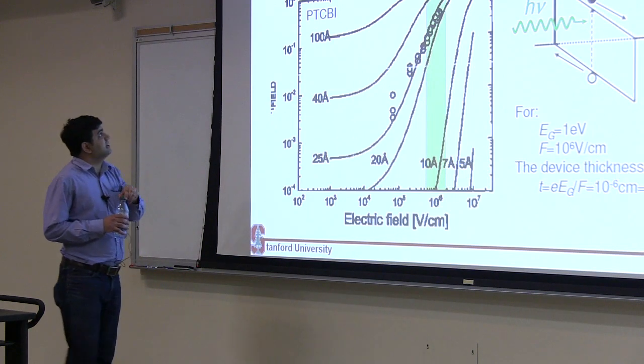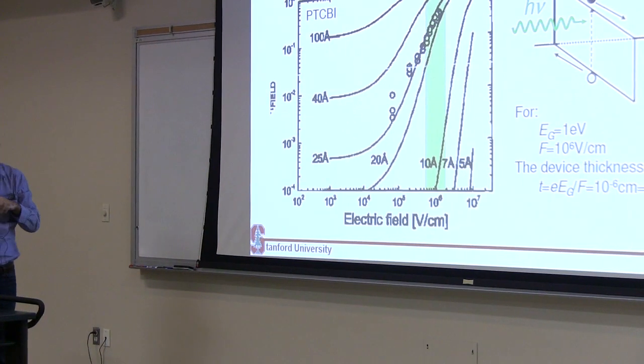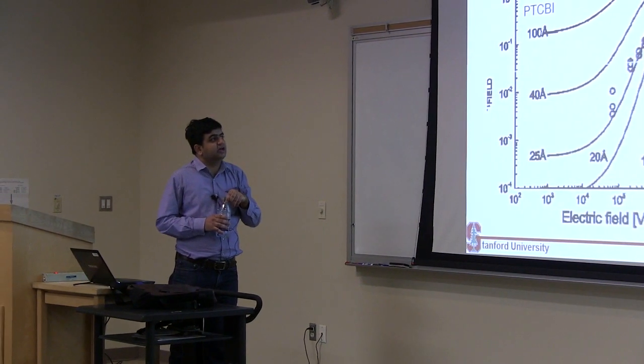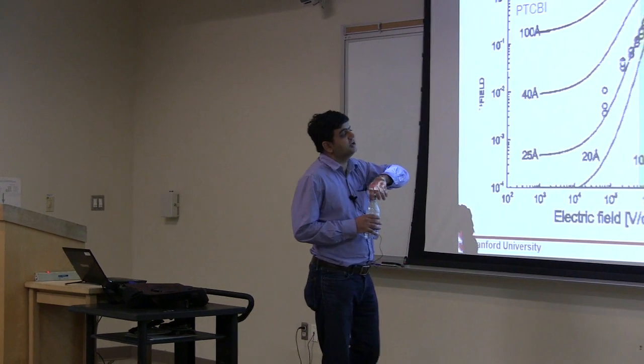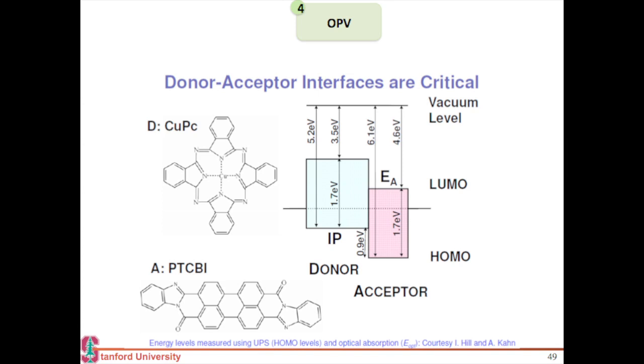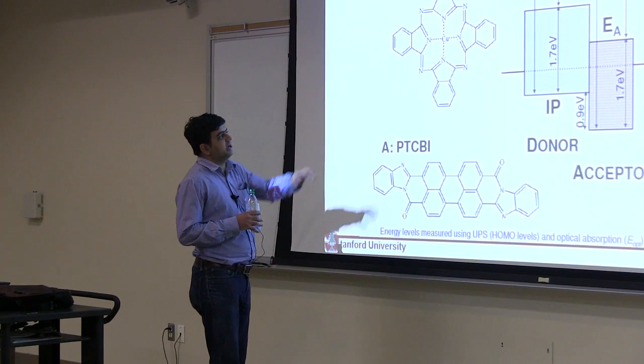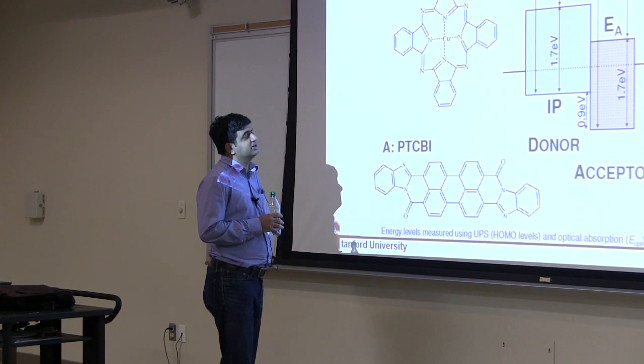The reason for that is that in organic molecules, electrons and holes are not generated separately — they're generated as an exciton pair. What people then discovered was that instead of having a single layer, if you use a heterojunction with a donor material, which has a lower electron affinity, and an acceptor layer with a higher electron affinity, you could immediately start to get efficiencies of 1, 2, 3, 4, 5% — just by using two layers instead of one.